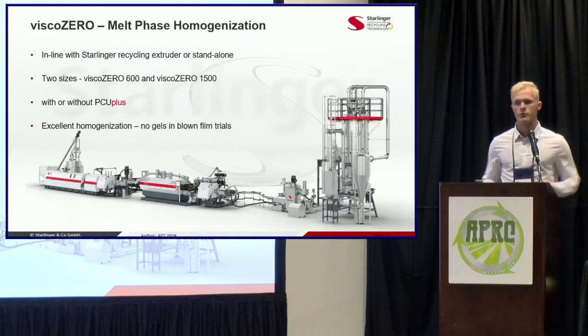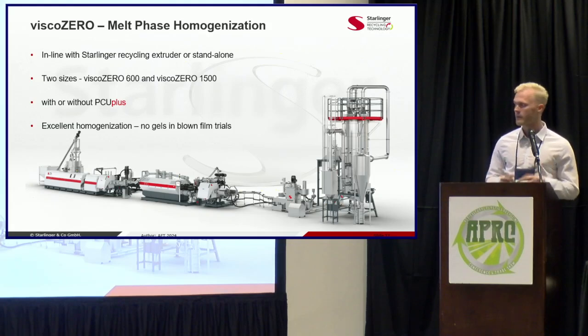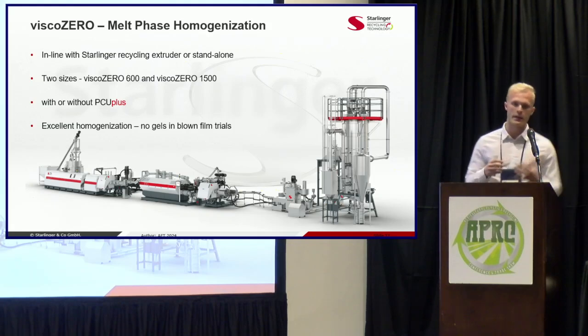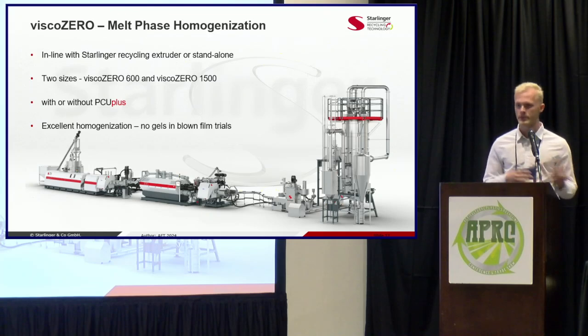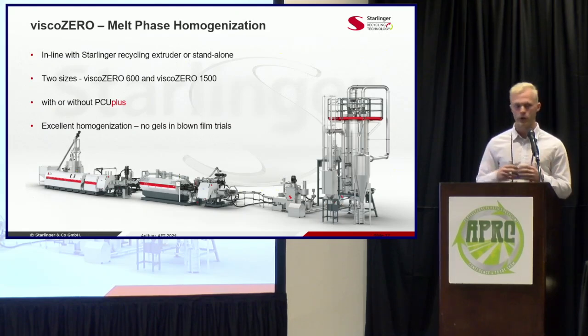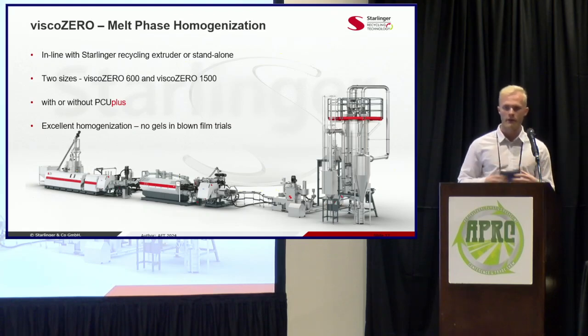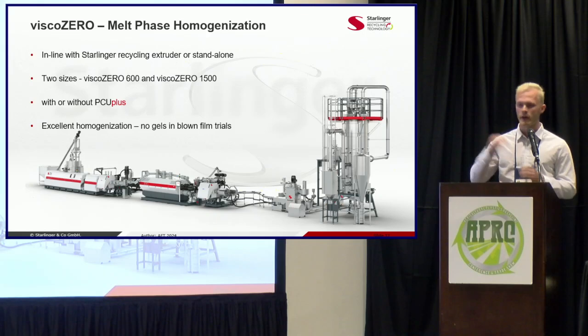So it doesn't have a traditional screw on the inside. It's actually a set of mixing arms. And depending, of course, on the polymer type, there's a different mixing arm design that's used. But the residence time is from 20 to 30 minutes, and it mixes the polymer together under high vacuum. So what you're doing is exposing the surface area of that polymer to the high vacuum and pulling off all of those VOCs.